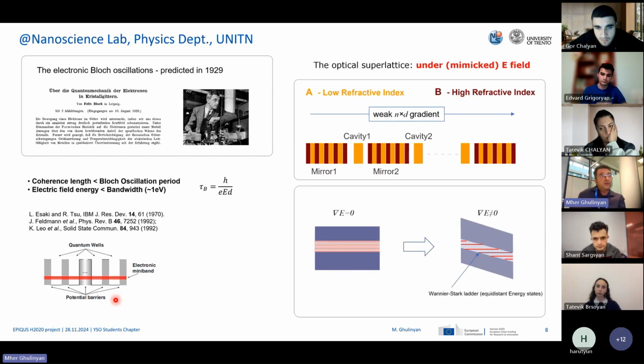So what we were thinking was to try to see this wave phenomenon in an optical counterpart. Photons are not charged particles, so if you apply an electric field, the photonic bands will not tilt. But there is a trick in optics, and this trick is applying a gradient of the optical path of the layers through the structure. Every time you repeat a structure, like the brown one, you change its thickness or its refractive index by a very tiny amount, and this creates a gradient through the structure. Of course, once you make a structure, this gradient is fixed, and you cannot change the bands as you wish, but it will provide a tilted situation of your photonic bands.